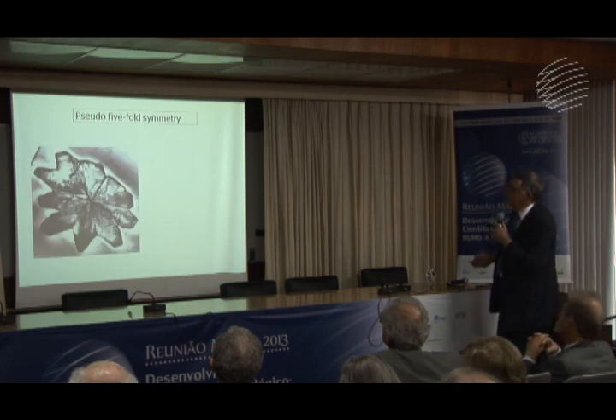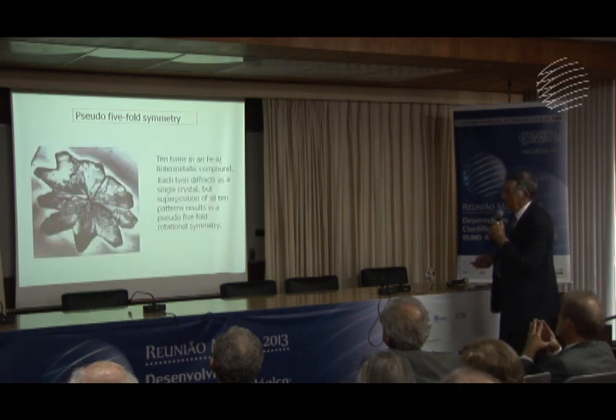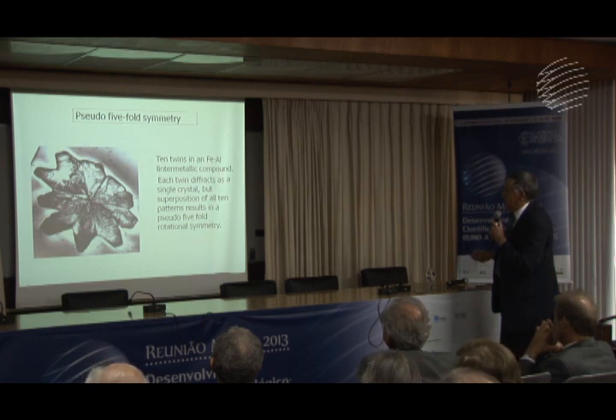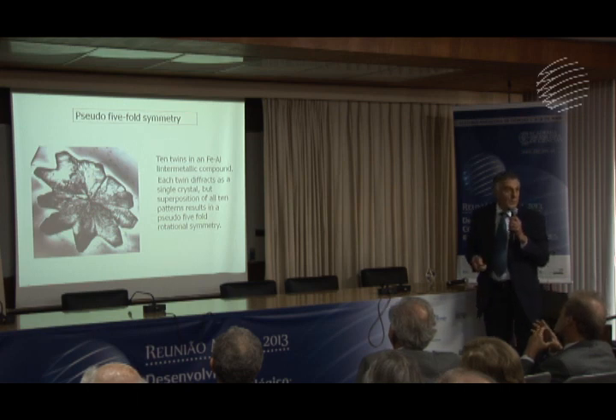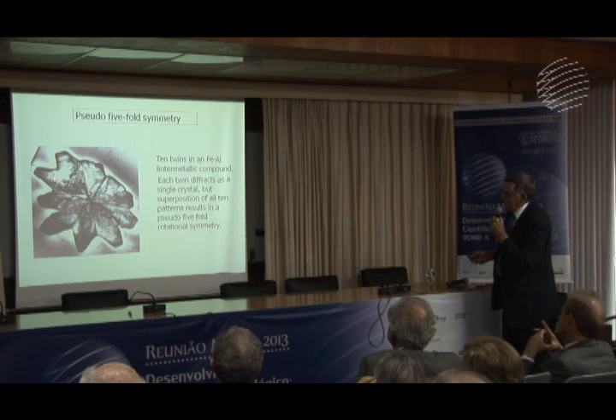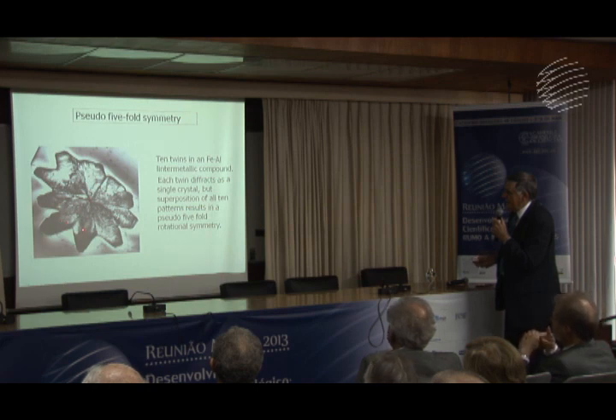Here is another example. These are very abundant crystals in the aluminum iron system. And they're quite large. You can see them with an optical microscope. And look at this flower. This is a single crystal on the left. Here is another one. Here's another one. If you count them, you see that there are 10 of them. But really, there are five, because this crystal here is exactly the same orientation as this. And this crystal here is exactly the same orientation as this. So there are five orientations here.